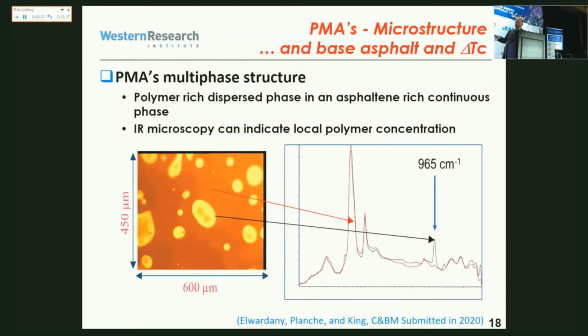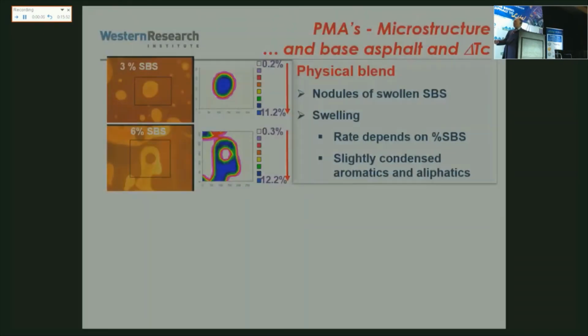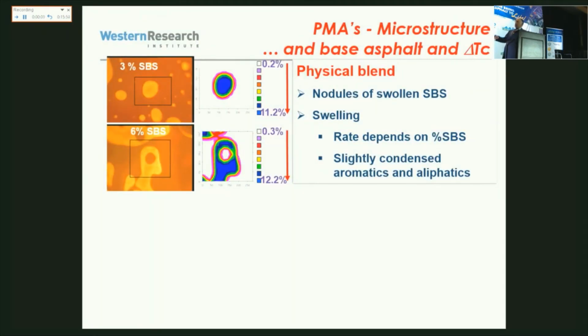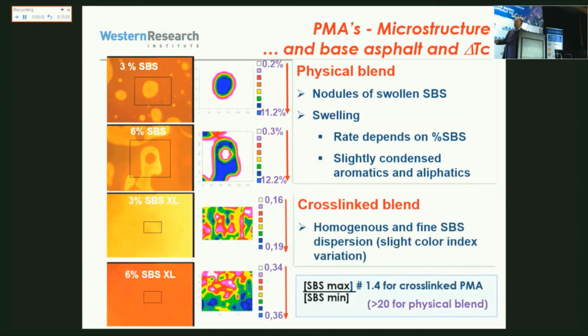So this can also be looked at with different technologies, and with infrared microscopy, we can even measure the amount of polymer that is in the nodules, polymer nodules, and what is the amount of polymer outside of them. So we can do very quantitative analysis, and we can look at physical blends, and we can look also at cross-linked blends, and we see big differences. And in cross-linked blends, it's very much homogeneous, and this has been known for some time, but this shows, I would say, more quantitative data.